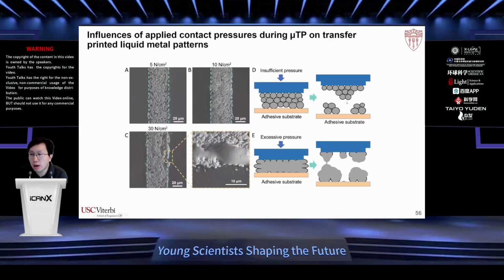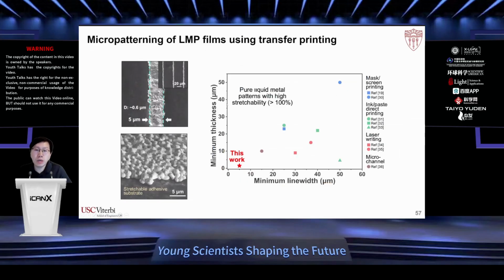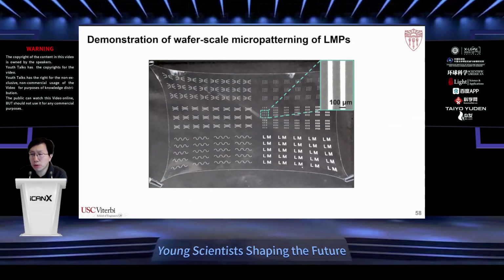We studied how different transfer printing pressure affects the final result, but eventually we can achieve 5 micron resolution, which is actually only a few particles in width. And in thickness, it's a single layer. So the minimum line width and the thickness are both within 5 microns. This is much smaller than what you can achieve using other methods for patterning liquid metal. And because both processes, self-assembly and transfer printing, are scalable, we can achieve large-scale patterning.